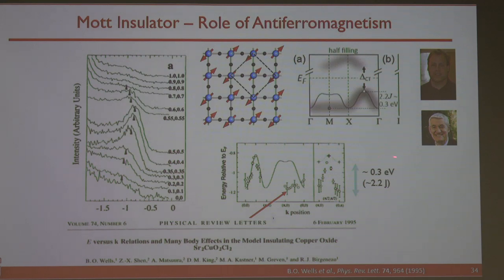And this is some of the early work, collaboration with Bob Birgeneau's group, when he was still at MIT, and you can clearly see that if you consider the spin exchange, then you can get a pretty good agreement, in the sense that the theory will predict the amount of dispersion is completely controlled by the magnetic interaction J. And J can be measured by the neutron data, and you can see a very good agreement along certain directions. But on the other hand, if you go to the zone boundary, you can see even the magnetic model has a pretty poor agreement. Okay? And that, remember, is where much of the physics happens.